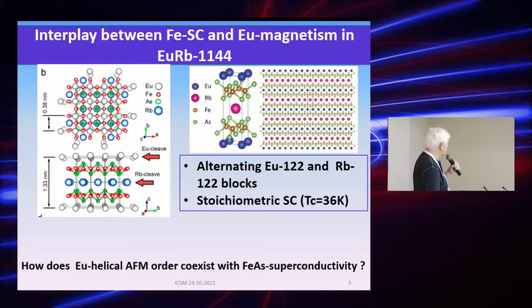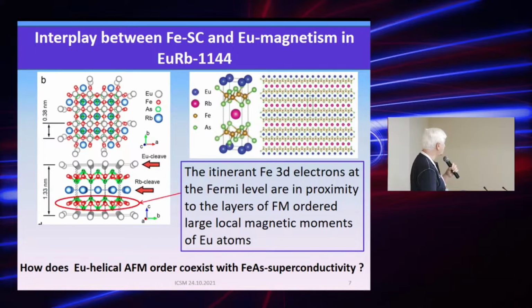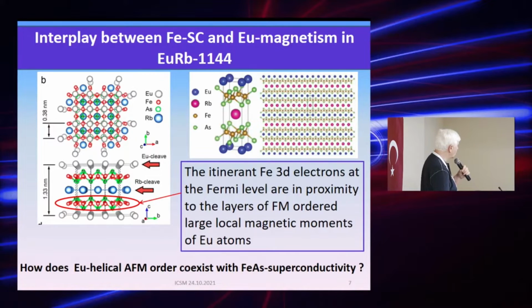So the size of rubidium atoms and europium atoms is different, and it also must be understood how the cleavage happened, because all the measurements happened with the vacuum cleaved, low temperature cleaved surface. So we first study how the native surface opens after cleavage. And what I want to add to the story is that the superconductivity occurs in between the rubidium and europium layers, inside the iron arsenide planes. So certainly I will show you the evidence that those orbitals which form the superconducting pairs come from the iron arsenide almost flat planes.